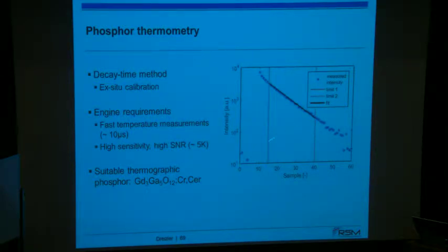Again, you see for this phosphor, this GGG doped with chrome, but as well as some cerium that has been added here to reduce the afterglow. So some of these phosphors do show, at a certain time after excitation, a long-lasting afterglow. And this afterglow can be reduced if you co-dope that with another material. And in this case, this was cerium.